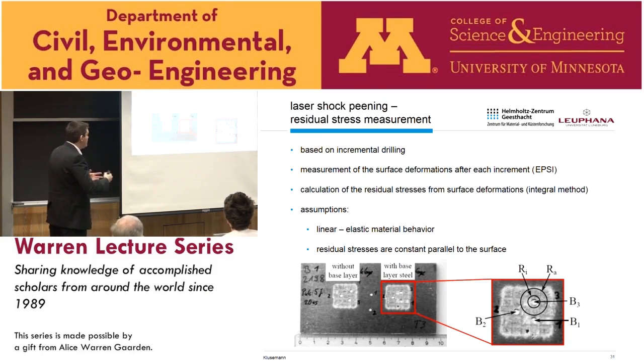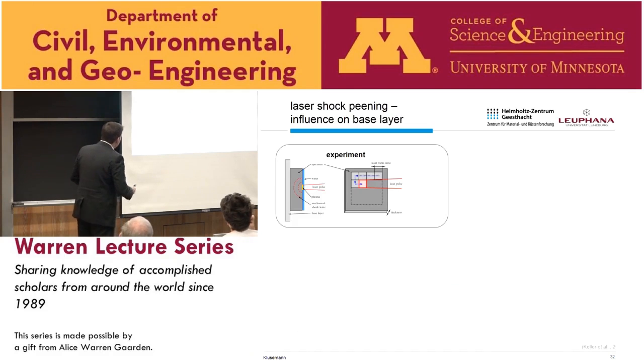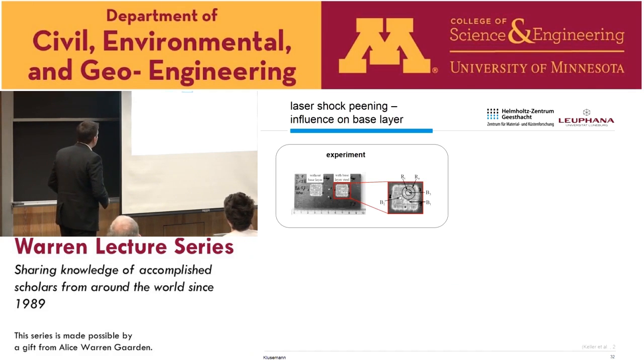Hole drilling is, we measure for that the surface deformation after each increment which we drill. And we can then, based on the integral method, calculate the residual stress deformation. I have clearly to say the assumption here is linear elastic material behavior and that residual stresses are constant parallel to the surface. This has to be clearly mentioned.